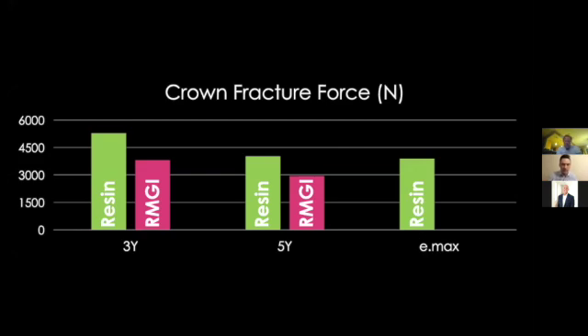So just to orient you with the graph here, because sometimes I see a graph and get a little bit lost. The graph is looking at the crown fracture strength. We've got the 3Y zirconia, the 5Y zirconia, and the Emax. And the green bars are when it was bonded with resin cement, and the pink bars are when it was cemented with RMGI cement. And a couple of interesting things we found. First of all, with lithium disilicate, great material, but when we used it at that thickness, if it was cemented with RMGI cement, it didn't survive the fatigue test to even get a strength value.